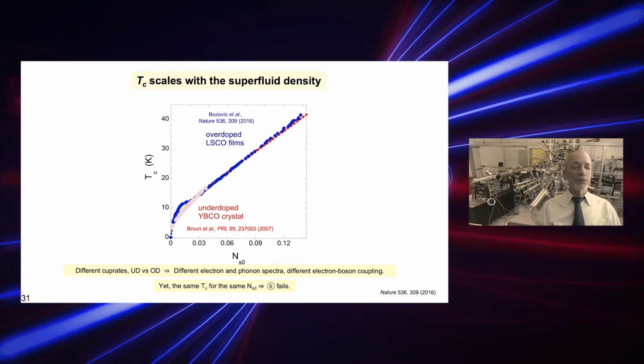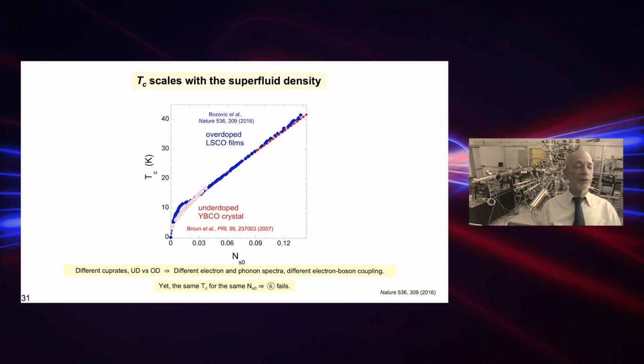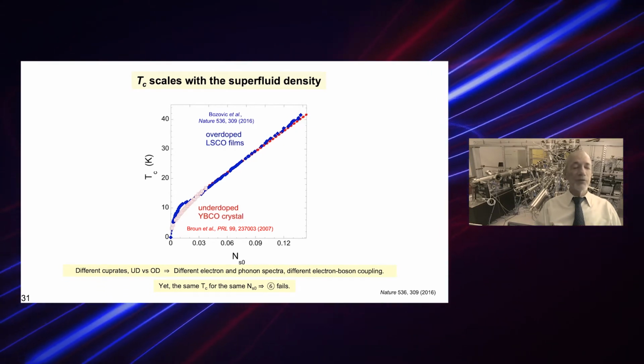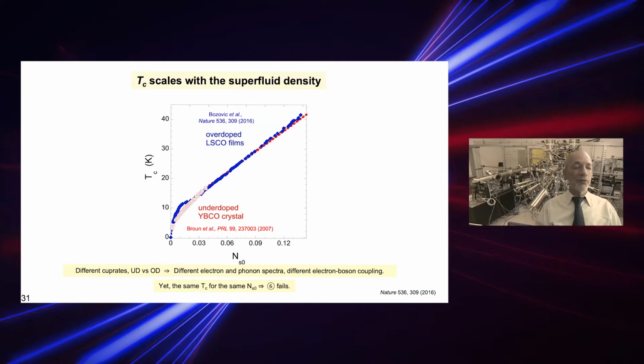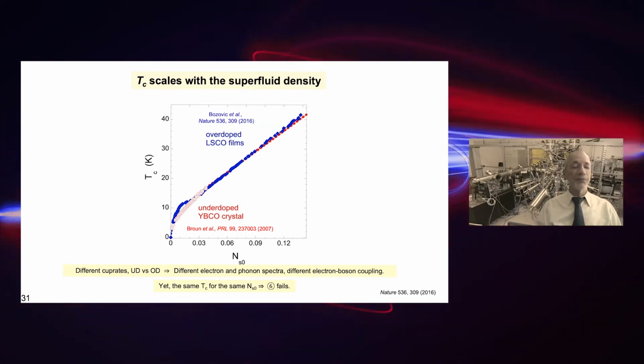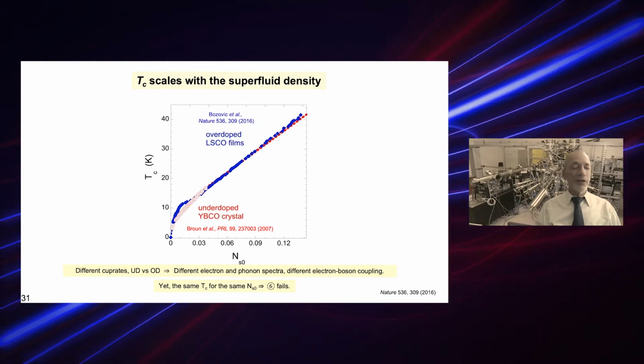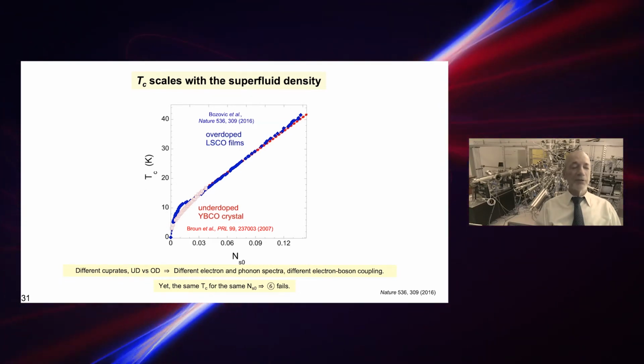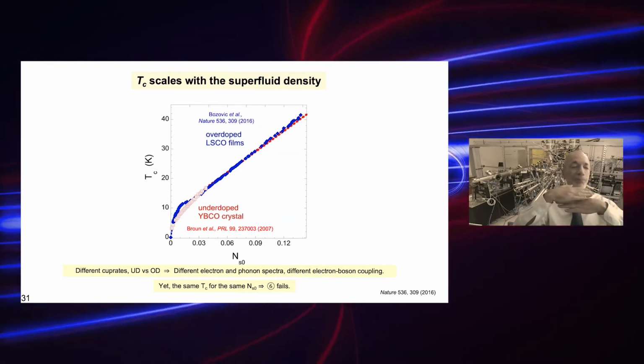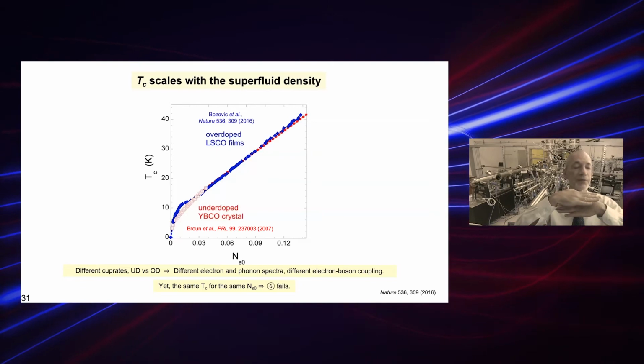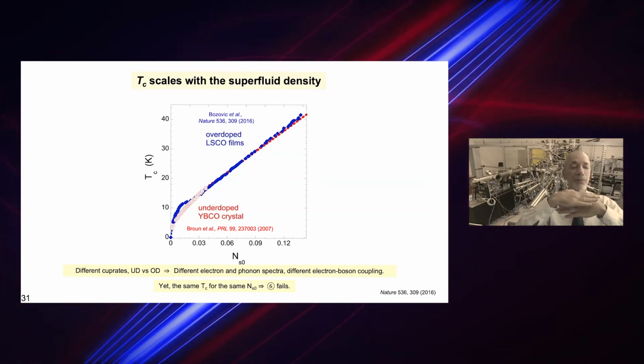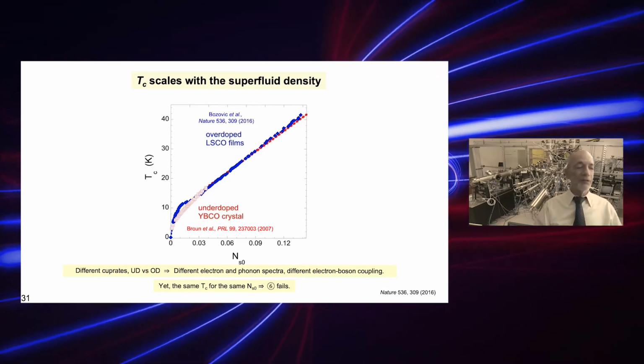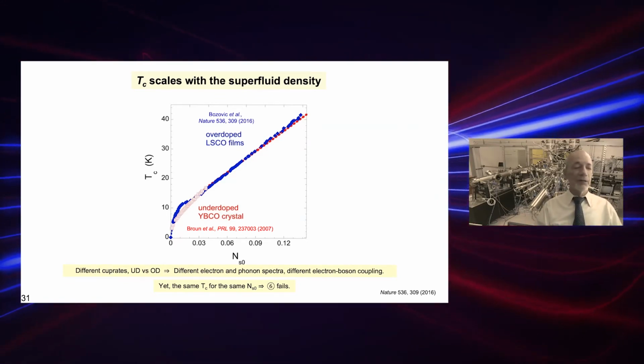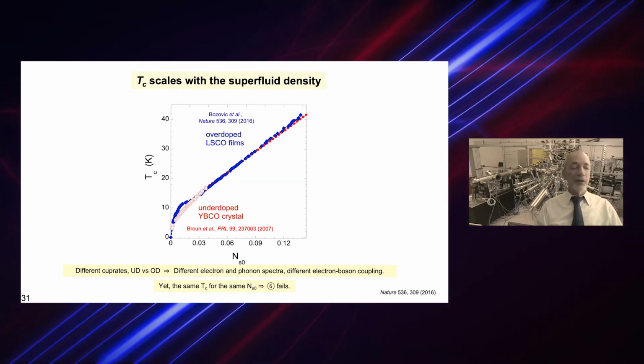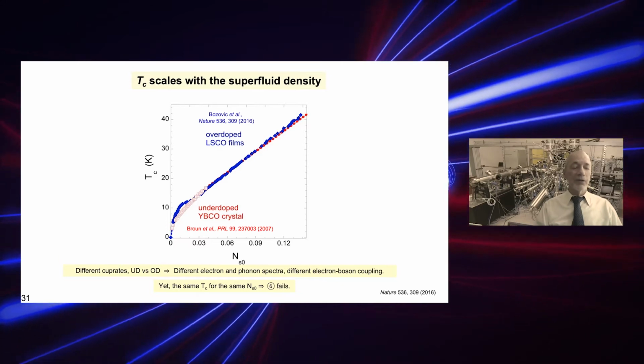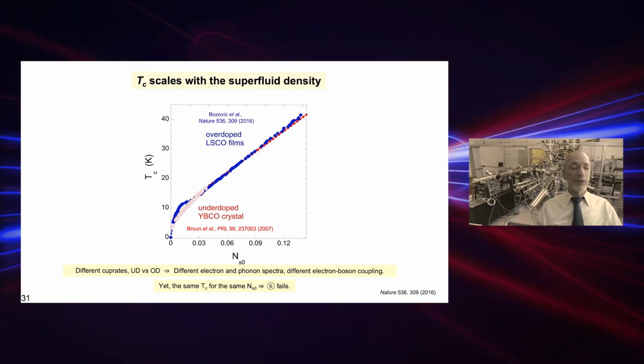Let me point out that almost identical dependence was seen in a different cuprate, YBCO, by a different group and using a different technique. Moreover, it was on the heavily underdoped side. This is critically important. YBCO and LSCO have very different electronic spectra. In YBCO, the electron bands from the two nearby copper oxygen planes are close to one another. They hybridize into bonding and anti-bonding combination, and they split, and they are populated to a different level. The phonon spectra are also different, and the electron-phonon coupling calculated using DFT differs by 300%.